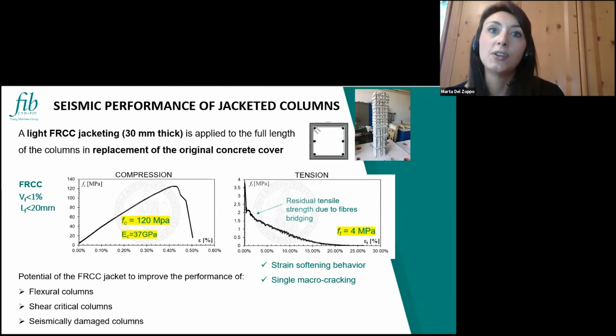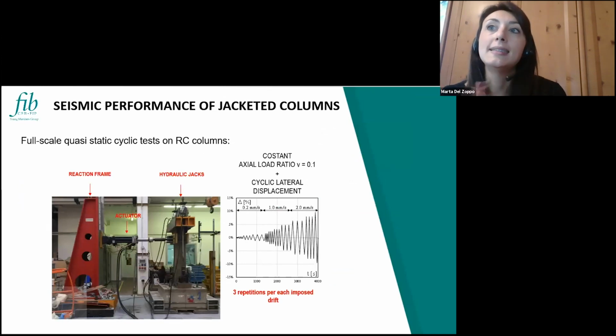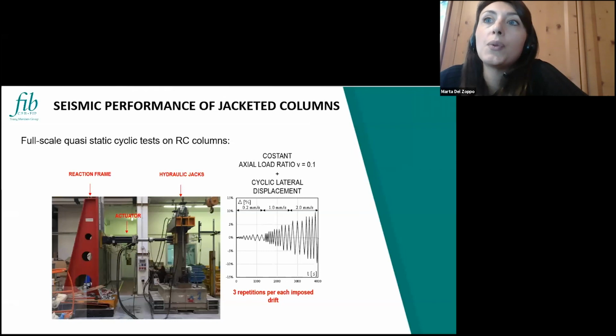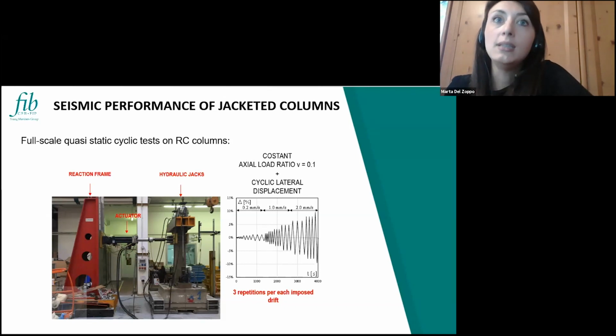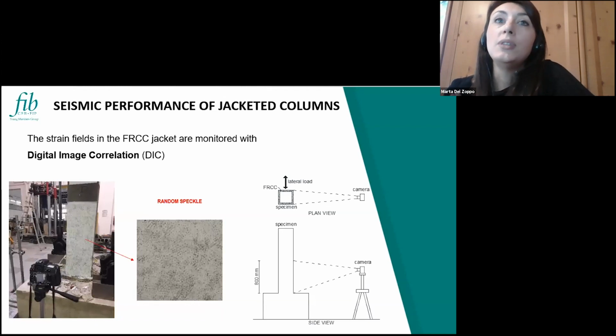And now we will see the potential of using such a jacketing technique for improving the performance of flexural and shear critical columns, and also for the retrofit of columns that have already experienced an earthquake and are likely damaged after this event. To assess the seismic performance of the jacketed columns, we performed full-scale quasi-static tests with this setup and load protocol, so cyclic lateral loading. And the behavior of the jacket has been monitored during the test by means of digital image correlation, a technique that allows us to track the behavior and the strain distribution on the jacket during the test.